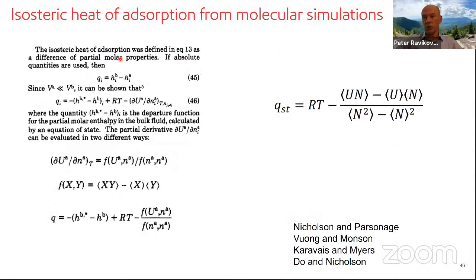And in molecular simulations, what we do typically is one uses the so-called fluctuation formula to calculate the heats of adsorption. I list here a number of classical references for how this formula is derived, and this is the end result. So it relates the fluctuations in the energies and the number of molecules adsorbed in the grand canonical ensemble, and relates it to the isosteric heat of adsorption.